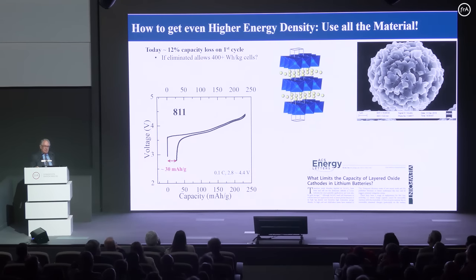One of the things we have to do, so we don't have to worry so much about the stability, is actually use all the material we have. A challenge in these materials is that you can take a lot of lithium out, but when you put it back in, the last 10 to 15% won't go back in under normal conditions. So this is a reduced diffusion. We're looking at that, and you can see what we call the first cycle loss. We have to get rid of this. We want to get to 400 or 500 watt hours per kilogram. And these particular materials, we say 811, that means 80% nickel, 10% manganese, and 10% cobalt.